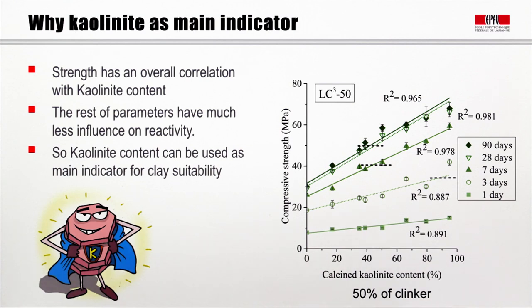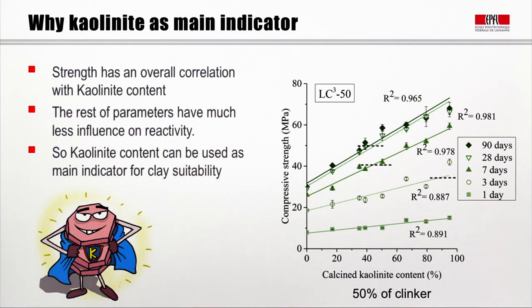These clays were taken from many different places in the world. They have different secondary minerals and many other factors varying, but those factors make very little difference because of the very high correlations we see just with the kaolinite content. So kaolinite content is really what you want to know about to determine if your clay is suitable.